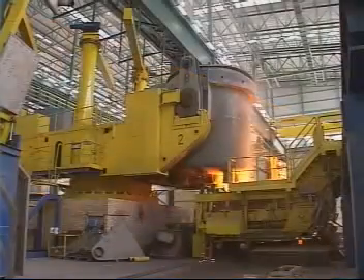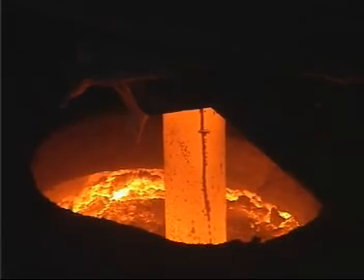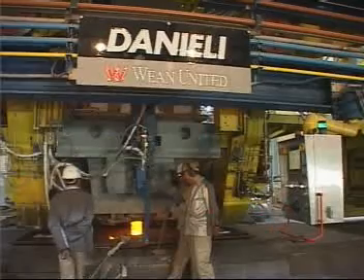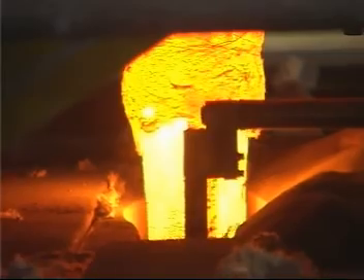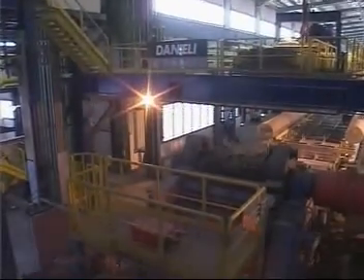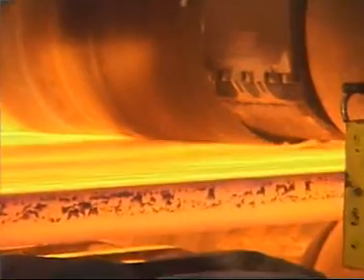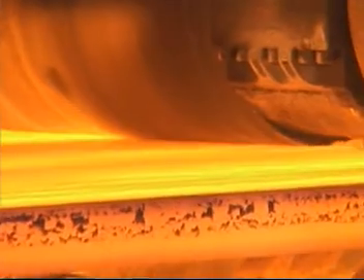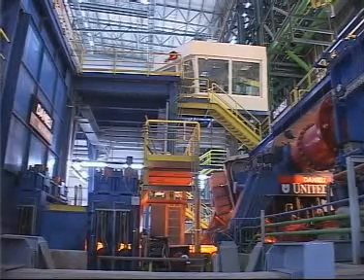In order to obtain the required product quality, considerable care was taken in designing a proper primary and secondary cooling system, as well as the bending and unbending units. Upstream the pendulum shear, a rotary descaler removes the scale before the slab enters the tunnel furnace to avoid damages to the furnace rollers. It is also possible to control and uniform the growth of scale layer thickness and composition.